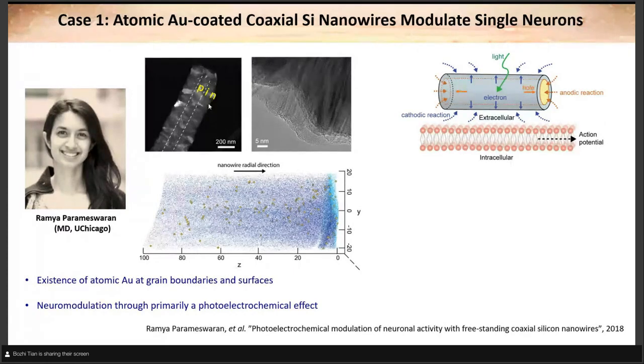And we characterized our materials, and what we found is that over the surface and the grain boundaries, there is a lot of atomic gold. And this atomic gold actually came from the starting gold nanoparticles that we used to catalyze the growth of the silicon wire. And we also found out that this atomic gold can promote the light-generated charge injection into solution, causing the electrochemical reaction. So now imagine we have built up this bio interface.